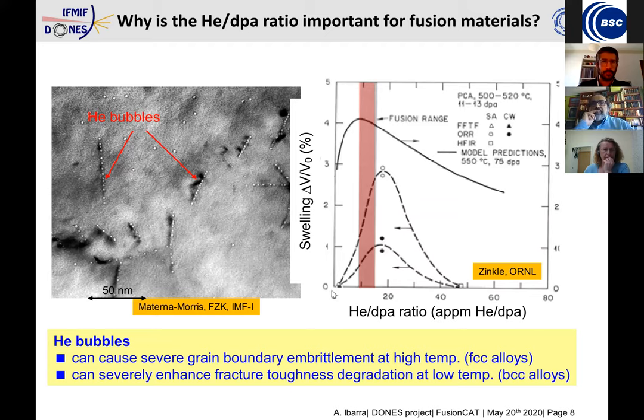And the amount of swelling is a function of the amount of helium that you have in the material. We usually measure the amount of helium using a ratio that we call the helium to DPA. This gives you an idea of the amount of helium compared with the amount of point defects that you have in the material. And you can see that there is a critical amount of helium that promotes the swelling in the material. This is because the helium, due to the presence of the radiation, is first generated, and second, it is able to move around in the material, and at the end, it is frozen in the shape of bubbles located along the dislocation lines. Of course, if we have bubbles, that means that we need volume, and that means that the material increases.